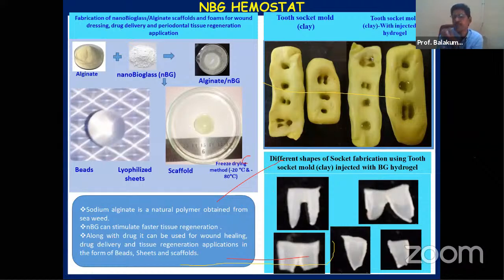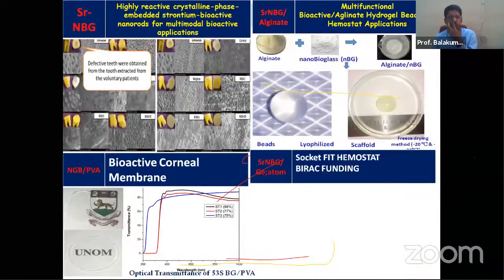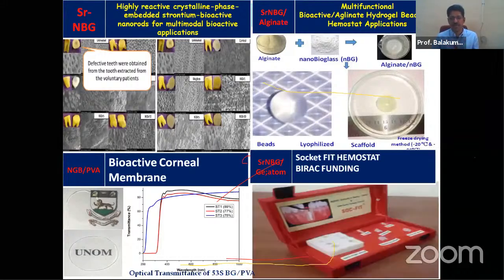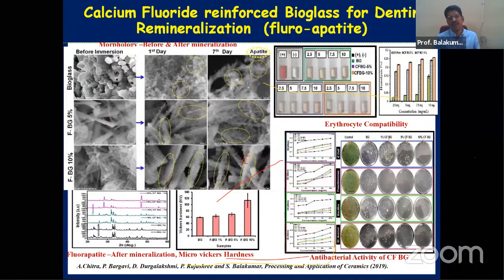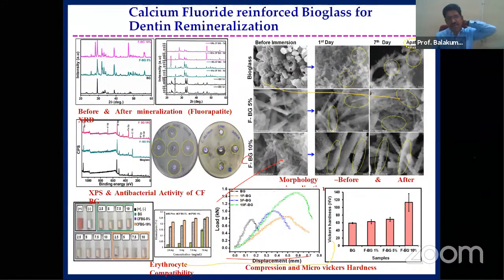This is one of our small achievements from our past 10 years of work. Later we were also looking at dentin remineralization. Dentin remineralization can be promoted with calcium fluoride. So the fluoride-rich bioglass we fabricated using different techniques, and we systematically established the structural properties, hardness, hemocompatibility, cell compatibility and antibacterial properties. And later we also evaluated the calcium phosphate content and the mechanical property. We found it is highly suitable for this.